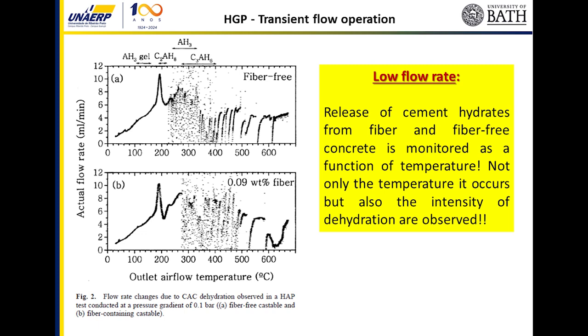This is what we get, for example, for a cement paste or a concrete. In this case, we have a fiber-free cement or concrete with the CAC cement, and we put 0.09% of fiber, polymeric fiber, polypropylene fiber, and then we heat. As we heat, in this case, you see very similar patterns, and the pattern is because of the dehydration, so we can track the type of the cement hydrate here. It's not a TG, this is a permeometry technique, because you have the flow and you have the signal out there. So you can track here the flow rate going out of the material.